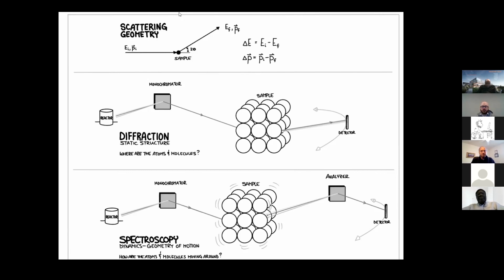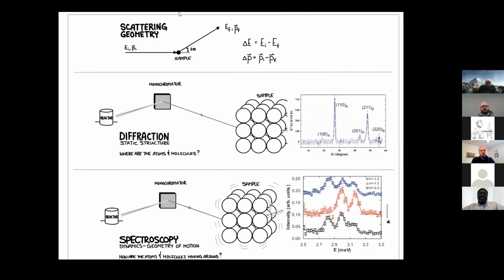In a spectroscopic experiment, same front end for that. You have a polychromatic beam that hits a monochromator. Monochromator selects off a narrow band of wavelengths or energies that scatters from a sample, but here you take all of those scattered neutrons and you analyze the energy of them at the back end so that you can distinguish what the final energy is, what the initial energy is, and do a subtraction to get what the energy was either gained or lost by your sample. And that, coupled with the scattering direction of the neutrons, gives you all the information that you need to basically determine the geometry of motion of what's happening at the nanoscale of your sample.